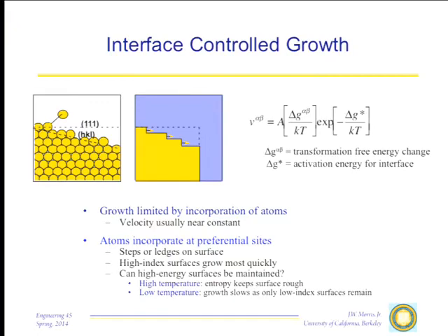When we have that situation, we have a rather serious kinetic problem. Because imagine that we have a surface which looks like it's shown here on the right initially. For some reason, we have roughnesses here. Here are the edges of various steps, and atoms are incorporated there. Well, that will cause the steps to progress. But before too long, the steps reach the end of the crystal and run out of their progression. And the crystal develops low index and distal surfaces, and in theory can't grow anymore.